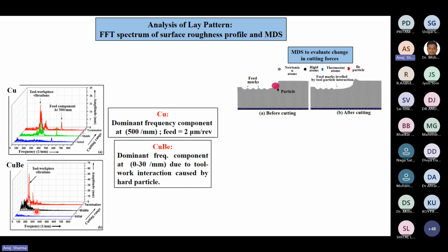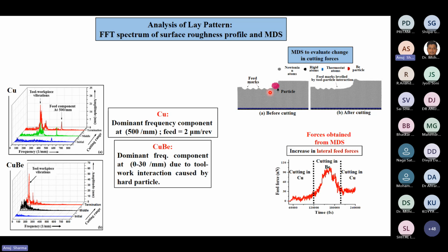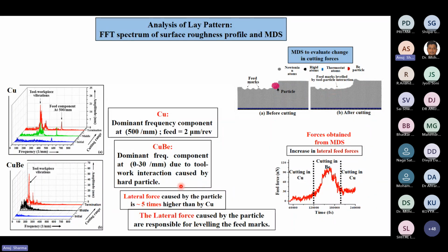Again, I carried out the MD simulation. I introduced the feed marks on the workpiece itself and considered the hard particle in the simulation. What I saw was that when the tool interacts with the particle, the tool has movement in the horizontal direction due to the force caused by the hard particle. So that levels these feed marks. It was also analyzed with the help of this force diagram, which showed that in the beryllium particle region, the lateral force becomes very high. That was seen with the molecular dynamics simulation. So that caused the movement of the tool in the lateral direction, which levels these feed marks. It was seen that the lateral force was 5 to 6 times higher than when it cuts in the copper. So lateral forces were responsible for leveling these feed marks.